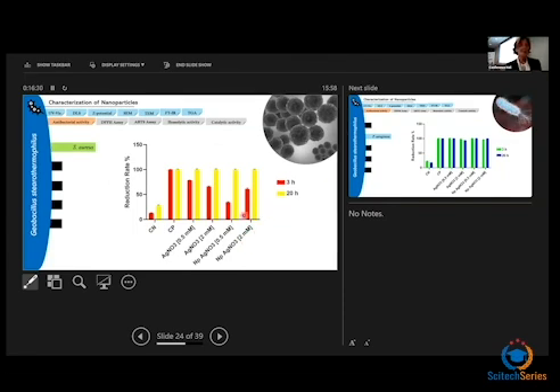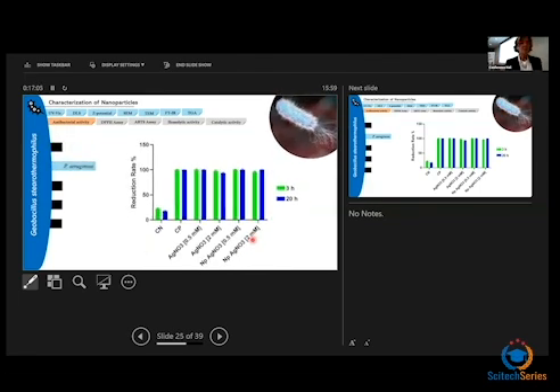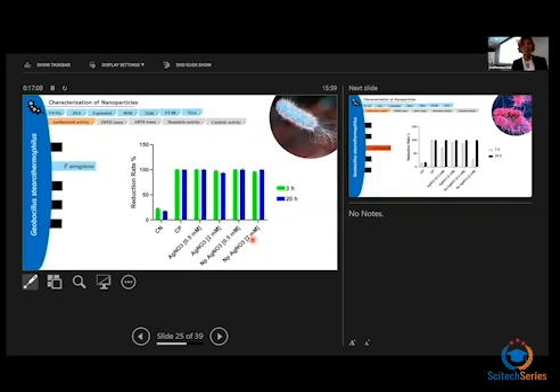In this slide, it is reported the bactericidal activity of nanoparticles used at a concentration of around 100 micrograms per milliliter, in which Staphylococcus aureus was completely killed after 20 hours of incubation with 0.5 and 2 millimolar nanoparticles. Pseudomonas aeruginosa resulted to be much more sensitive to the treatment with the nanoparticles, as cells already died after 3 hours of incubation, as we can see in this part.